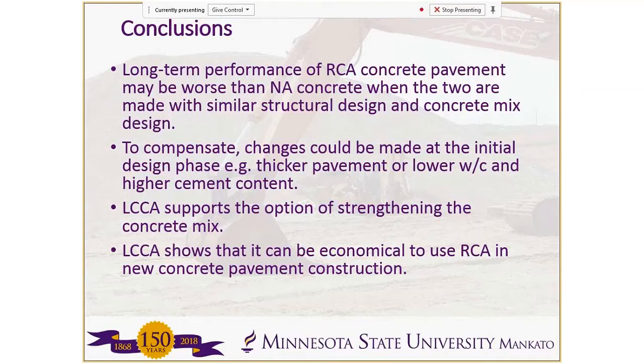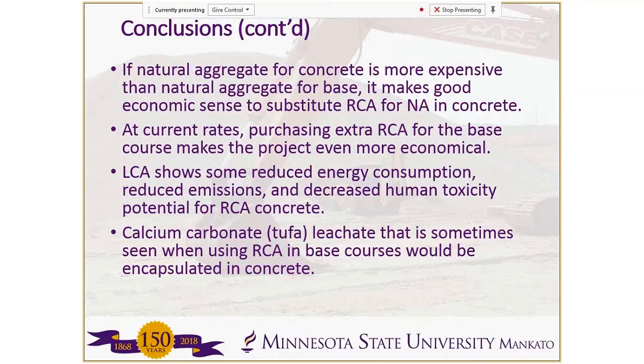The life cycle cost analysis supports the option of changing the mix design rather than increasing the thickness of the pavement. LCCA showed that it was economical to use the RCA in new concrete pavement. That turned out to be the most economical alternative. Which also makes sense because natural aggregate for concrete is usually a higher quality than the base natural aggregate. So if you can use the RCA to substitute the aggregate in the concrete, it should make good economic sense to do that rather than for the base course.